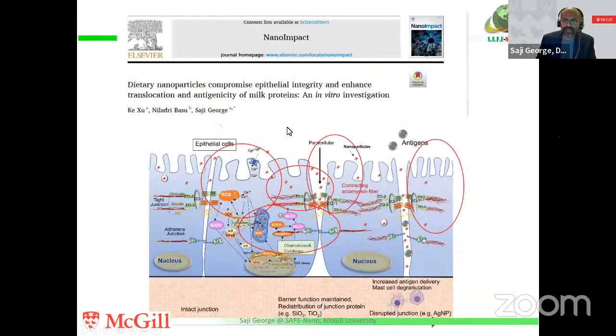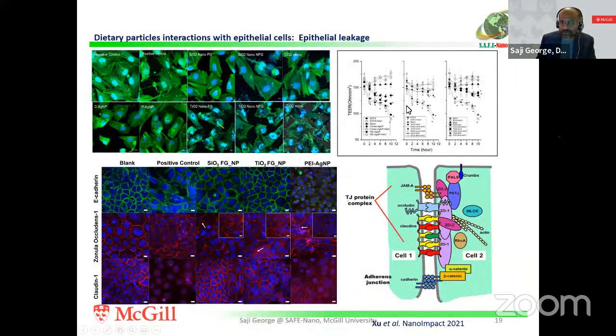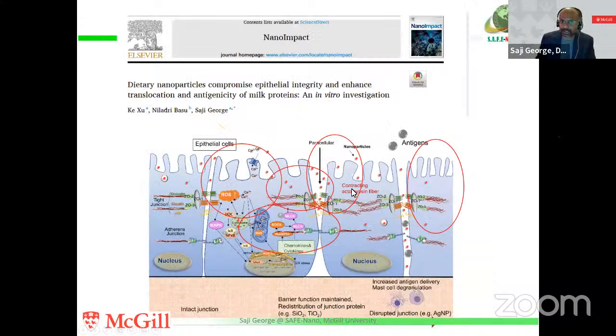And so we can see, when you look into it, that something is actually happening as a function of oxidative stress. That's another thing that we wanted to see. And as a result of oxidative stress, there is an inflammation. There are inflammatory markers, and we believe that in the case of silica and titanium dioxide, it is those inflammatory markers that actually cause the retrieval of those proteins that make the junction tight.